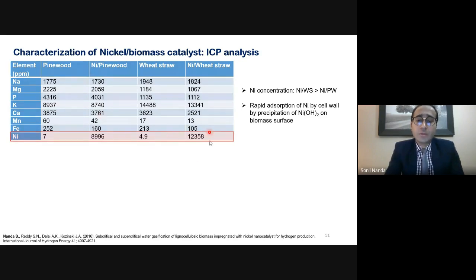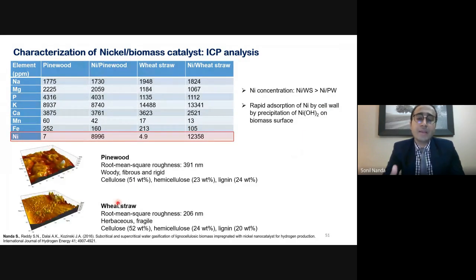But wheat straw, being a herbaceous residue, resulted in higher accumulation, because we added the same amount of nickel nitrate to both the feedstocks. Wheat straw resulted in superior accumulation or adsorption of this nickel compared to that of pine wood. This was because of the makeup of the wheat straw itself. Wheat straw is a porous material and a herbaceous residue, whereas pine wood is a woody material. It's highly fibrous and it contains more lignin.